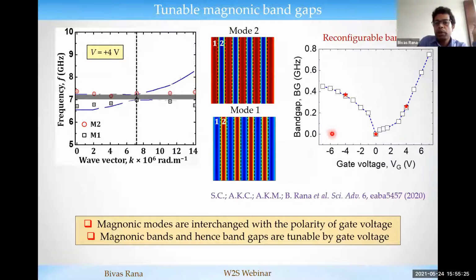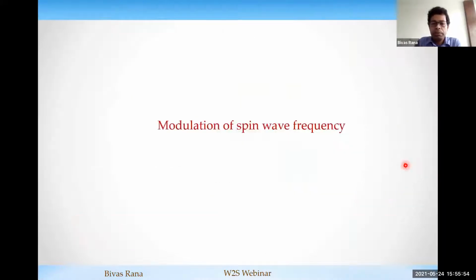So we measured how this band gap is varying as a function of gate voltage, and you can see you can tune the band gap from 0 to about 1 gigahertz just by applying a gate voltage of about 6 volt. So these are the important features of the magnonic crystal created by voltage control magnetic anisotropy.